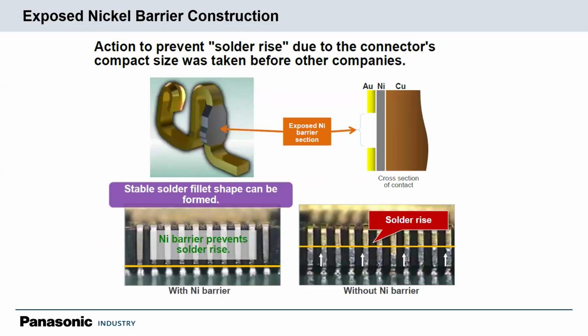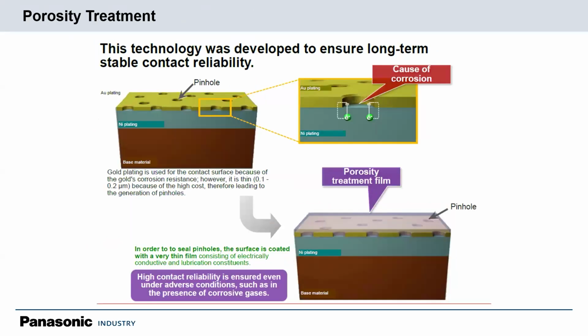There's also a nickel barrier on all of our contacts, so this prevents solder rise after reflow, and we were one of the first companies to adopt this type of technology. And lastly, a porosity treatment. With gold plating, sometimes pinholes can form in the plating, which can be a cause for corrosion. To combat this, we treat all of our contacts with this porosity treatment film. Essentially, it seals off these pinholes and gives it the same performance as a thicker layer of gold.